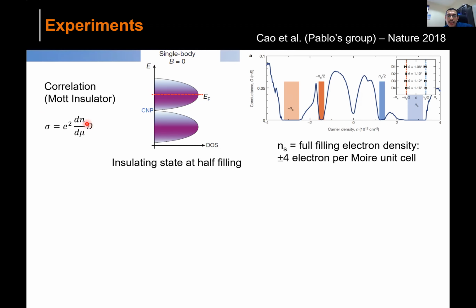In this case, it is not that the density of states goes to zero; the conductance goes to zero because your diffusion is zero. As I was saying in the last slide, the electrons are localized because of this half-filled state. Because of this interaction energy, although they have a density of states, they are not able to move. That's the reason they see exactly that at half filling. This is one of the main important observations in this field: at half filling, you see the conductance go to zero.